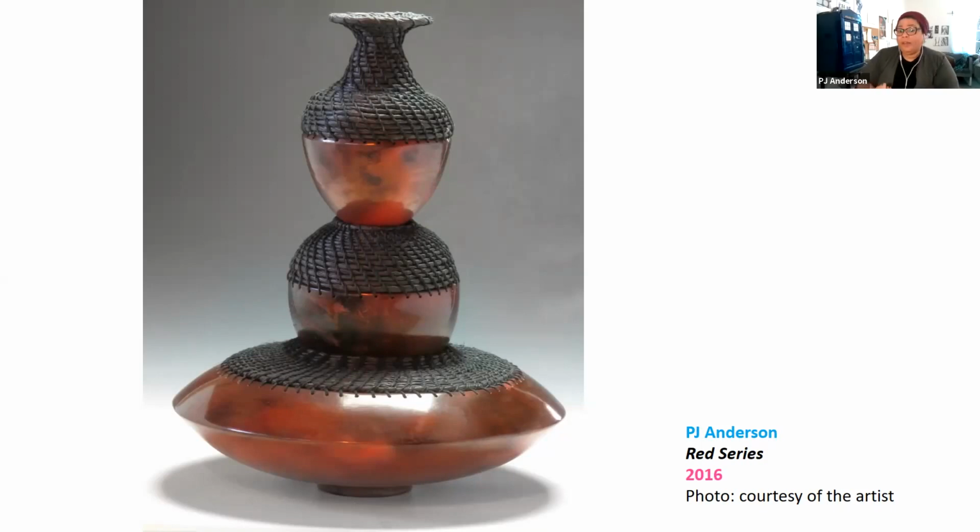Sure. I do it before, when it's still in the leather hard stage. You have to make them a little bit bigger than you think you're going to need because you have your shrinkage to deal with. And then there's also the terra sigillata that you have to put on later. So you want to make sure your holes are big enough so they don't get closed. And I'm using a paper that is used mostly for caning, like making furniture. So like Danish cord, or I don't remember what the plain one is, but it's just craft paper that's tightly twisted. You can get it in some colors, like black and white, but mostly black, white, and craft paper color. You can get it at Lee Valley.